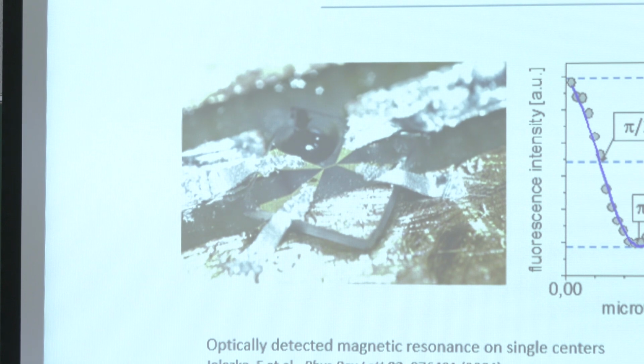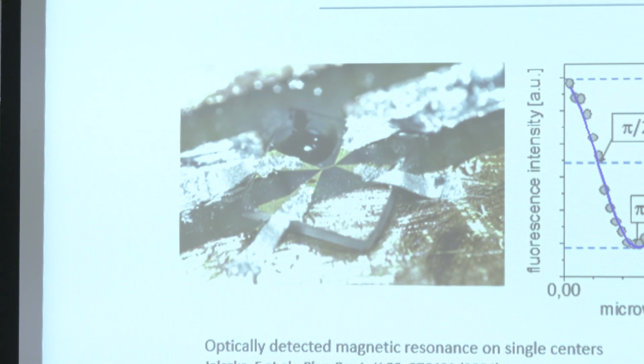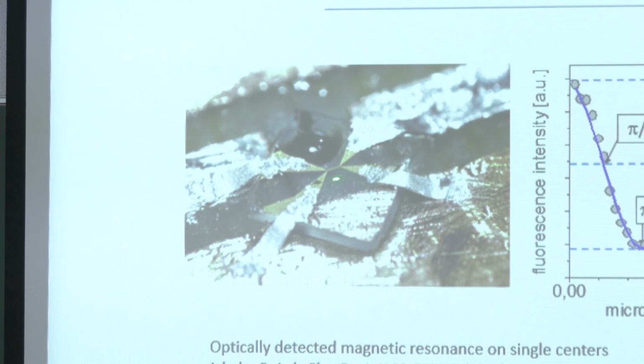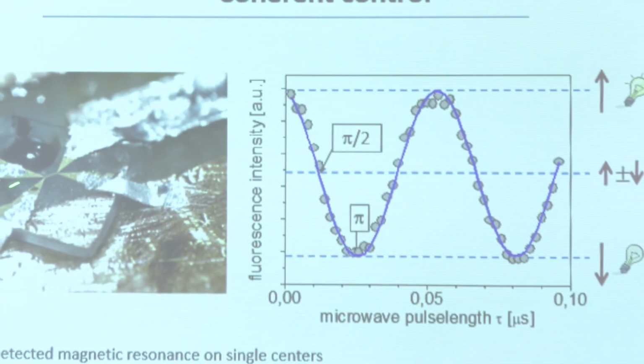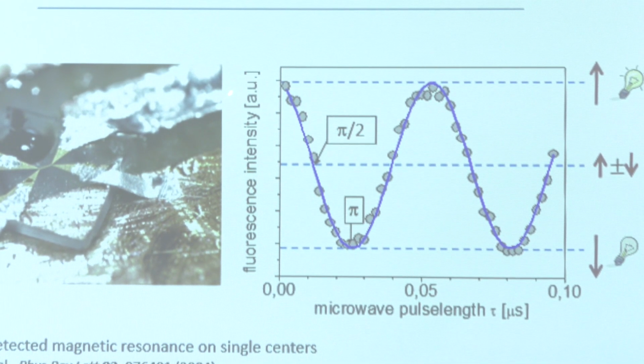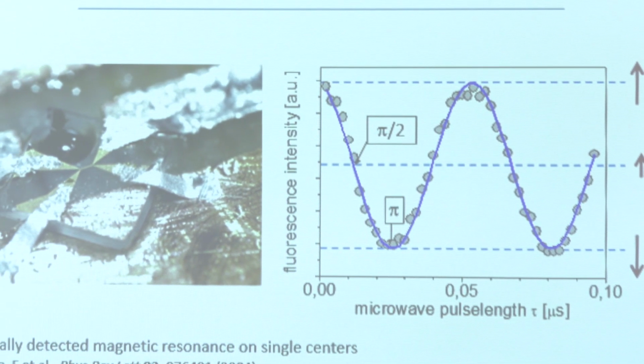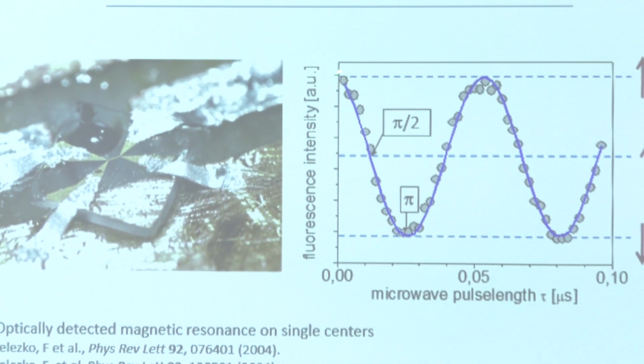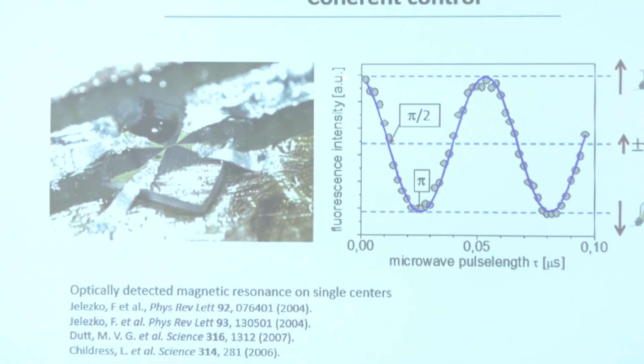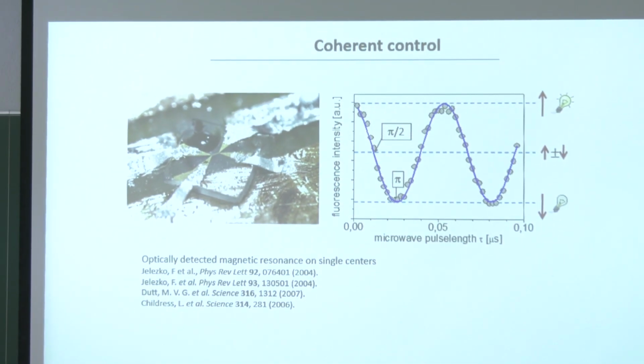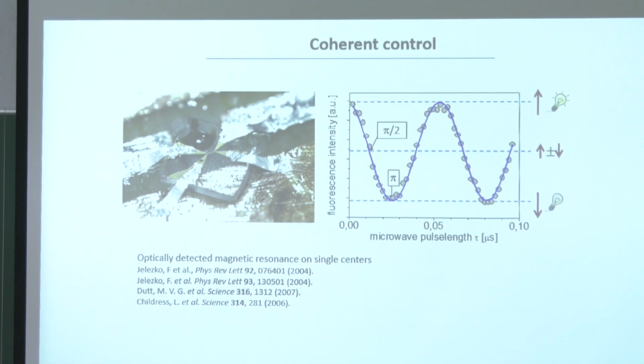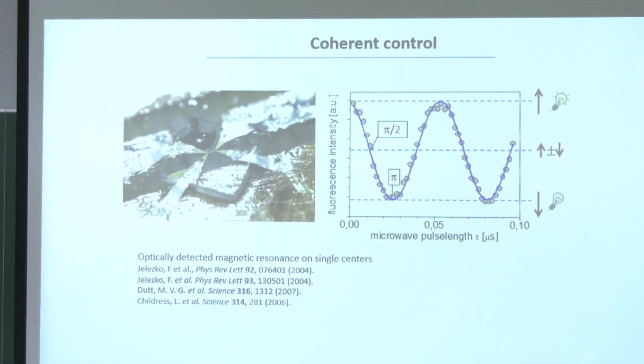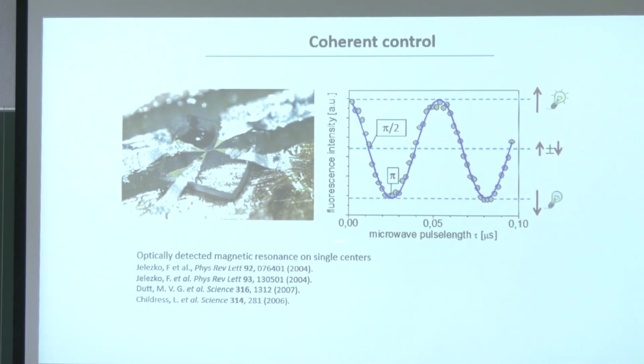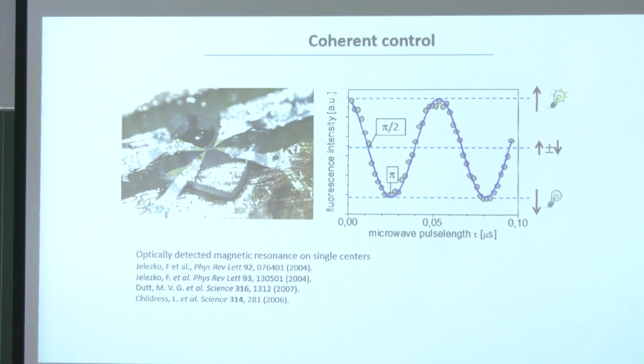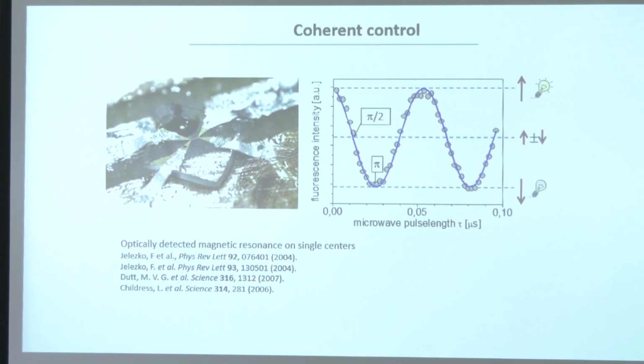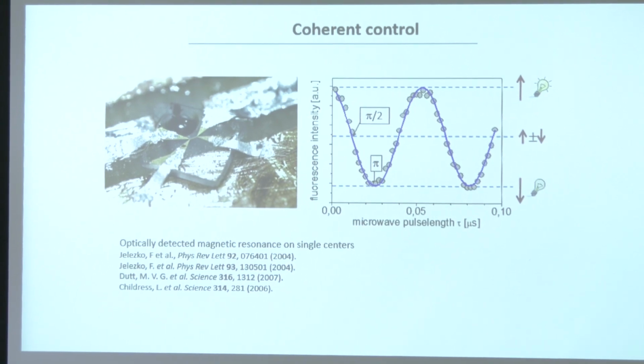The microscope lens is not shown here. It's coming from the top, and the photons that are collected are plotted versus, for example, the length of the applied microwave pulse. And what you see here is an example of Rabi oscillations, again measured optically. We measure the population of the bright state of the NV center, and you see that this population oscillates. That gives you a very basic coherent control experiment, driving a single spin using microwaves, and it also gives you the time scale of this drive. It can be done with Rabi frequencies reaching a few tens of megahertz, so you need just a few nanoseconds to flip the single spin.